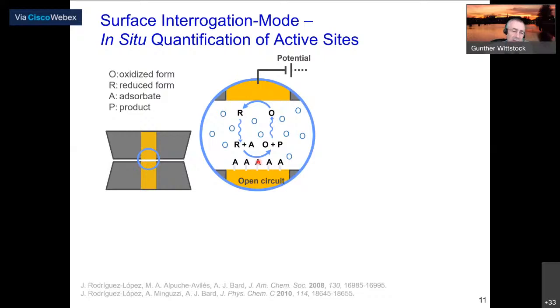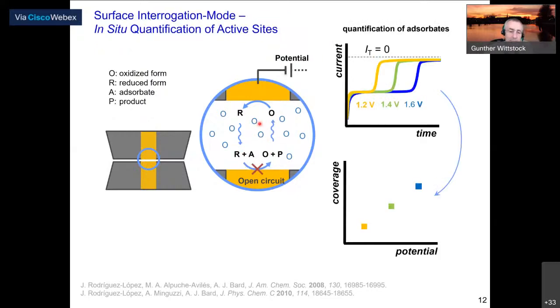So then as long as we have this oxide layer there, we establish this feedback loop by which the mediator is regenerated. But at one moment, we have consumed all of our layer because it's a finite amount. There's no resupply because there's no connection to the external circuit. And then the feedback loop stops and the current returns to the current which we would expect for hindered diffusion, because then only mediator molecules leaking in from the side of the cell can be oxidized.